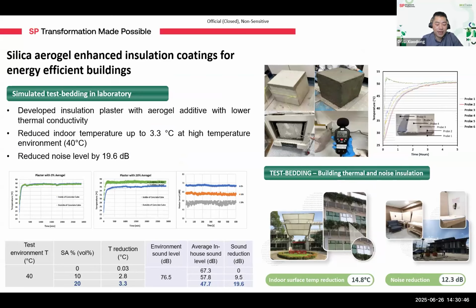In one simulation test, we coated a hollow concrete box with the aerogel-infused coating, placed it in a 40°C oven, and used thermocouples to monitor the temperature through the material. With about 20% aerogel content, we observed a temperature drop of 3.3°C, a significant boost in insulation performance. And aerogel's high porosity also makes it a natural sound insulator, with a sound reduction of 19.6 decibels, ideal for noisy urban environments.